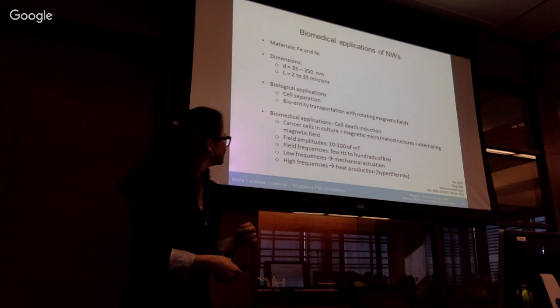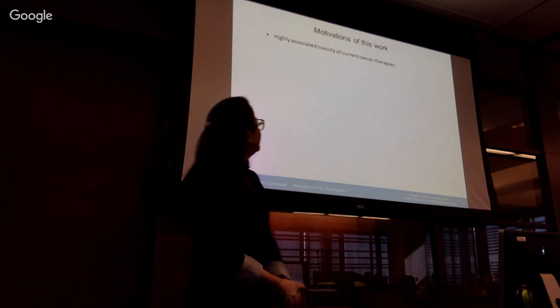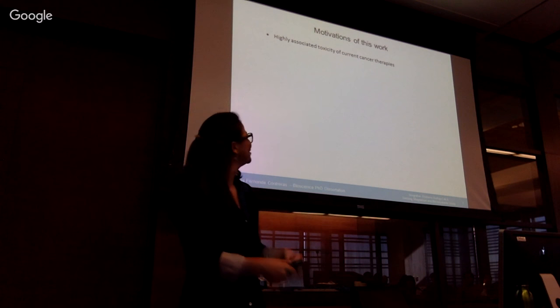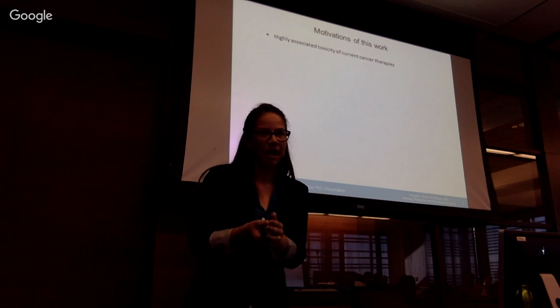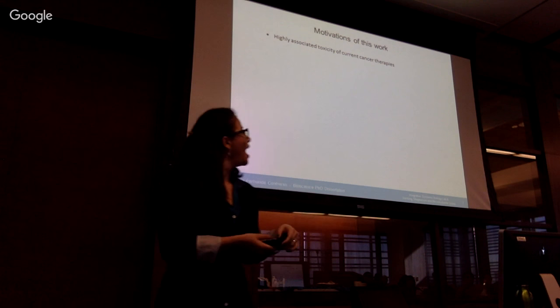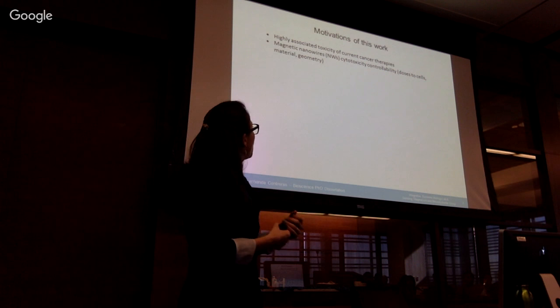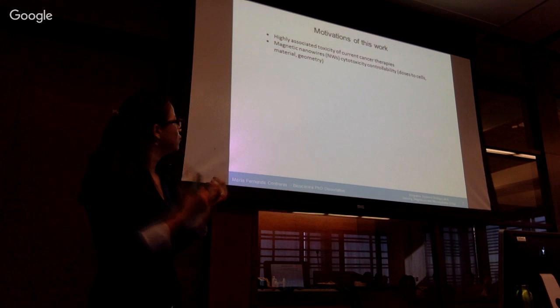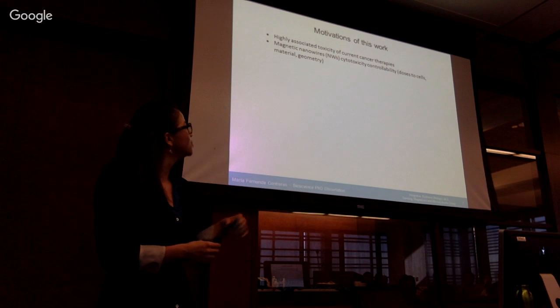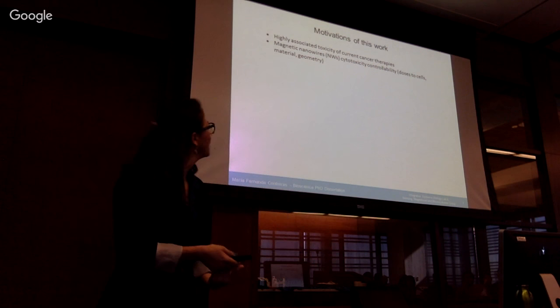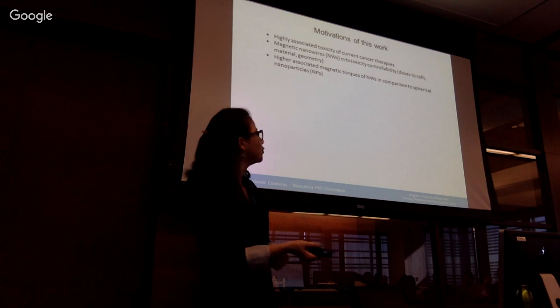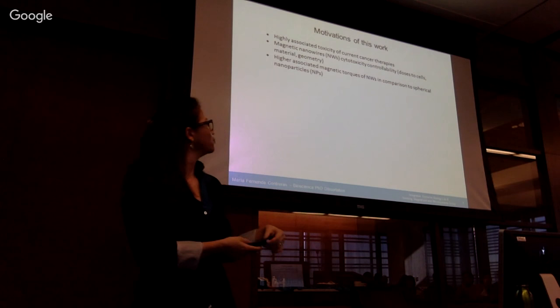Okay, so all this together motivated this work. Mainly, due to the highly associated toxicity of the current cancer therapies, we wanted to come up with an alternative treatment that would rely only on mechanical actuation, mainly on the oscillation of the wires. That would have lower associated toxicity. And why nanowires? Because you can control how toxic they are. If you choose a material and a less extended geometry, and also, of course, you can always choose the doses you add to cells, you can minimize the toxicity they exert by themselves to cells in culture. But especially we chose wires because they have higher associated magnetic torques when you compare with the typical spherical particles that are currently used in the field.